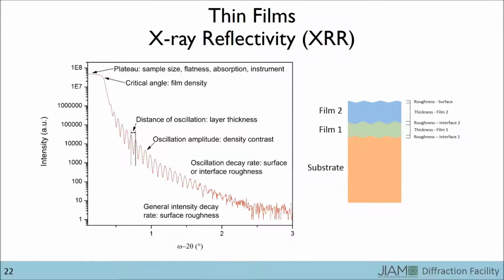While explaining the physics behind XRR is outside the scope of this video, I will say that the oscillations that you see are due to the interference of the X-rays reflected from the surface and the X-rays reflected from each of the interfaces. Because of this, the oscillations give us information regarding the thickness of each film, the roughness of each interface, and the density of the films and substrate. Using software available in the diffraction facility, you can determine values for each of these sample properties.